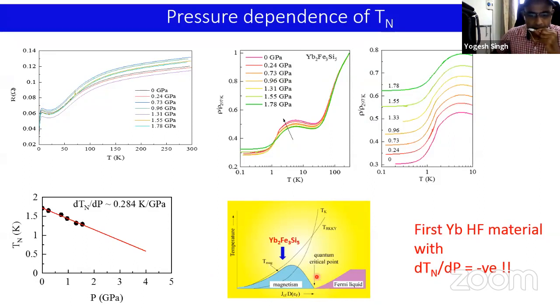So if the ytterbium were located on this side of the diagram, pressure would push it to the left, and therefore the TN would go up. However, our TN seems to be going down, and therefore we can conclude that our material sits on this side of the Doniach maximum. By the way, this is the first ytterbium heavy fermion compound with a negative dTN/dP. So out of all the hundreds of ytterbium compounds known, this is the only compound which shows this, to our knowledge. So this is special already.